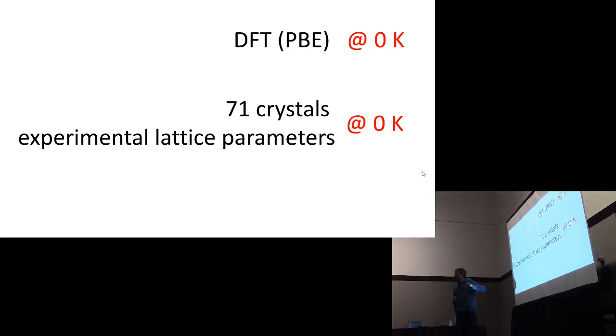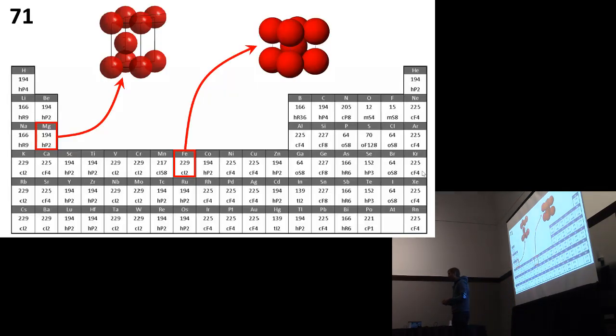What is the game we will play? We do DFT calculations always with a PBE functional, which is obviously at zero Kelvin, and we want to compare that with experimental values made in similar circumstances, also zero Kelvin. We need high quality experimental lattice parameters at zero Kelvin. If you start searching for these, you don't find them too easily. So we had to limit ourselves to a set of solids that was well studied over time. One possible choice were the elemental crystals, every element of the periodic table in their ground state structure.